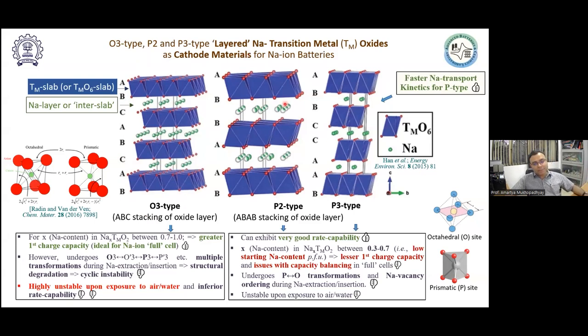Because when it comes to the other type of structure, where the sodium ions have a prismatic coordination, it cannot form with a sodium content of more than 0.7 per formula unit. So the starting sodium content is lower when it comes to a prismatic coordination or a P type of structure. So P indicates that the sodium ions are in prismatic coordination. So that's a disadvantage of the P type structure. Now, but for a prismatic coordination, the sodium ions can move from one prismatic site to the adjoining prismatic site directly. So the sodium transport is comparatively faster in this type of structure.